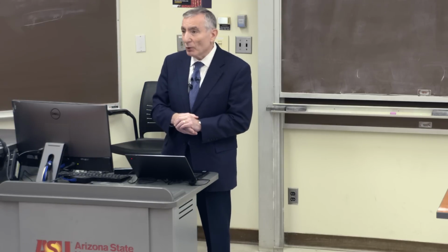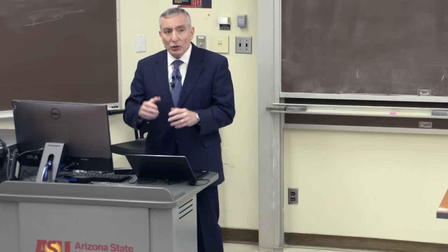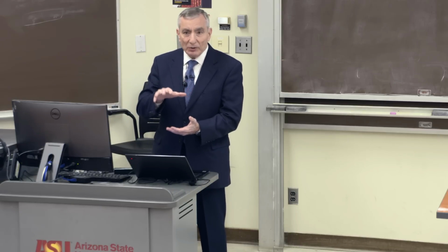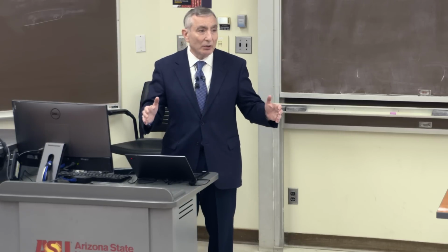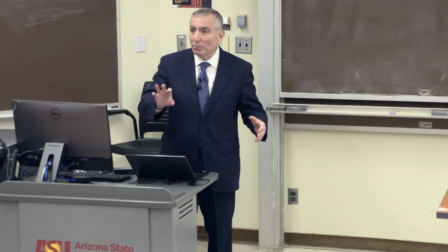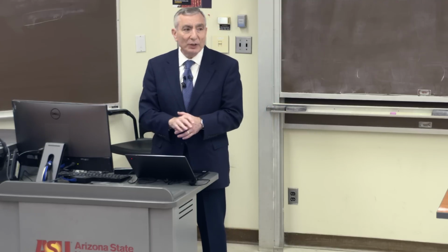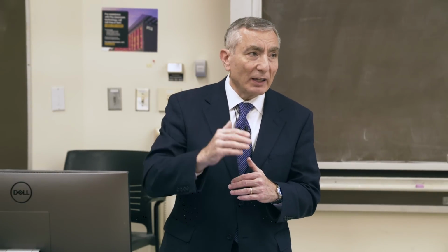So in other words, if you're working with cement and concrete, you buy a bottle from them and you add this liter of material to a cubic meter of your cement. And you blend that in and then make your concrete out of that. So they sell the master batches. The same thing with asphalt. It's a complete replacement for the styrene butadiene rubber in asphalt. And by doing that, it raises the working range by 11 degrees centigrade.